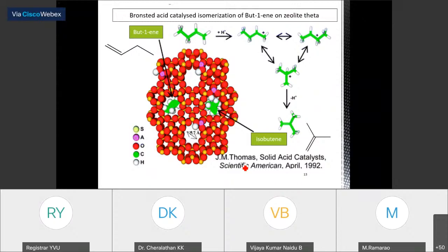So you can understand how a zeolite is catalyzing the reaction. For example, you can take butene isomerization into isobutene. I have a zeolite here, this zeolite theta, and I have channels and cages here, and in the channel or cage, I have a Brønsted site. You can imagine this as a Brønsted site. It is the active site. So when the molecule approaches, it should enter into the channel and reach the active site or acid site, and only then will it be converted into the product. So essentially, the reaction will be controlled by the pore because the active sites are present inside the material, inside the cages or channels.